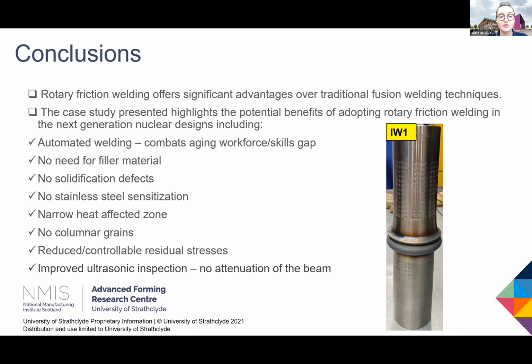We can also reduce and potentially control the residual stresses by controlling the welding parameters, which is an interesting piece of work that we'd like to explore. And we also can improve the ultrasonic inspection because there's no attenuation of the beam because there's no columnar grain formation.